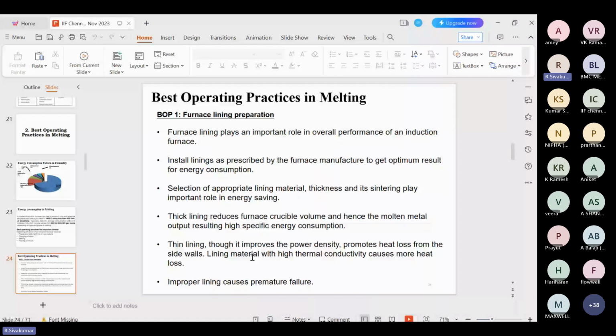Do not increase the lining thickness at the bottom or side walls, because every foundryman follows these practices; we are well aware. Increasing the lining means reducing the capacity of the furnace, and it leads to increasing energy consumption. That means power consumption is increasing.